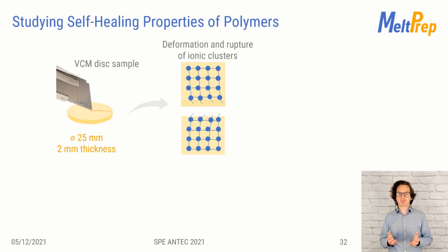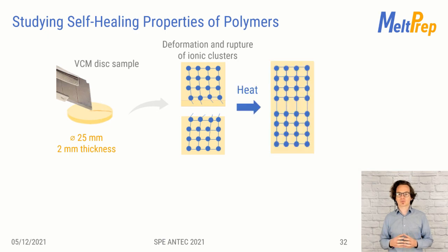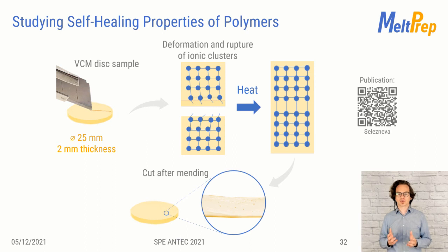A VCM disc sample was cut, resulting in the rupture and the deformation of the ionic clusters. Then the material was slightly heated again to observe the subsequent healing process. VCM enabled constant pressure on the sample without applying shear or squeezing the sample too much. This study allowed scientists to focus on the structural composition of the material and the properties of its constituents.